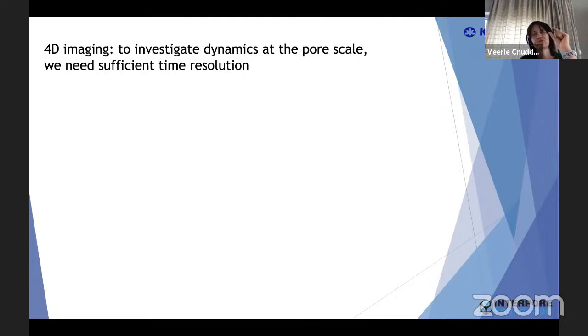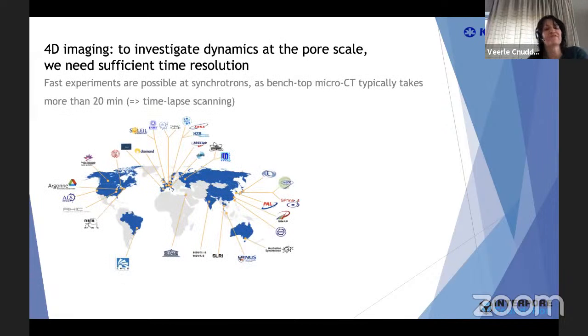But if you want to visualize something which is changing faster, let's say in 2 hours, that means with CT you want your sample to be stable during rotation. So you need a very fast scan, for instance, which takes a few minutes. You can scan the first few minutes, then after 20 minutes, then after 40 minutes, in order to visualize the process.